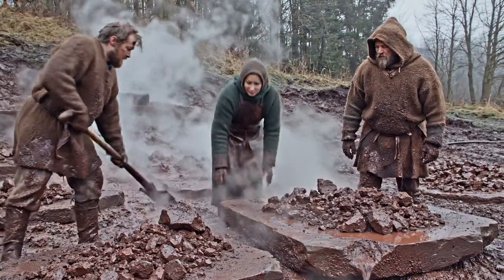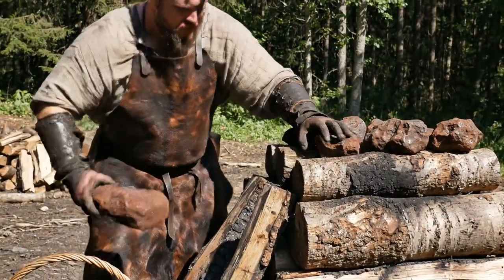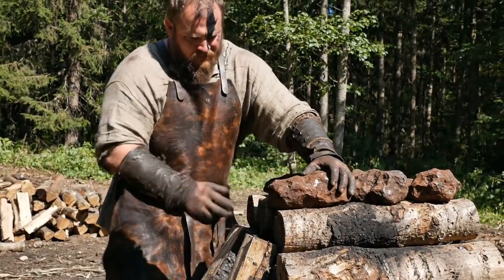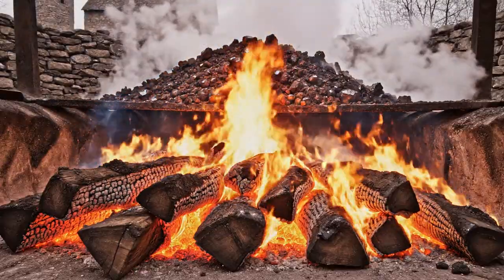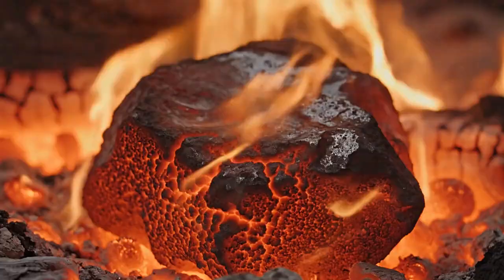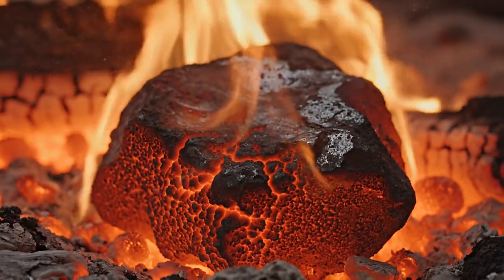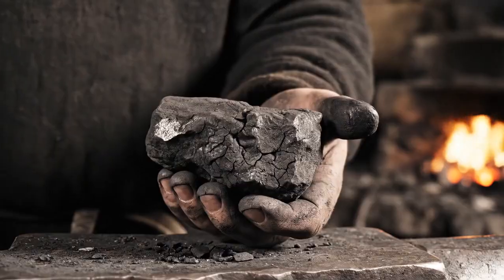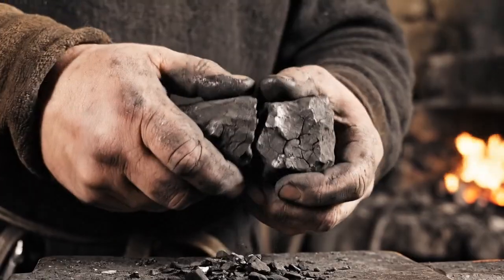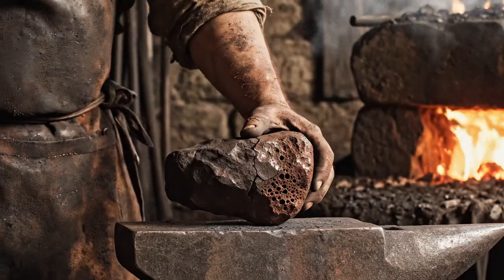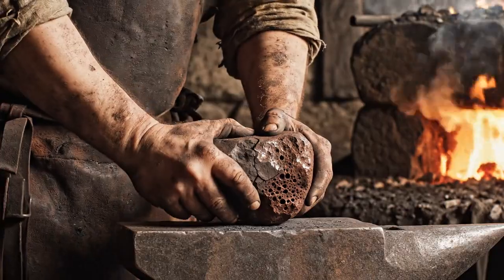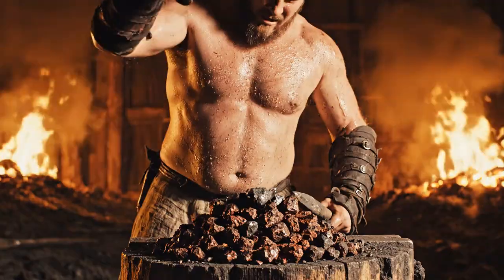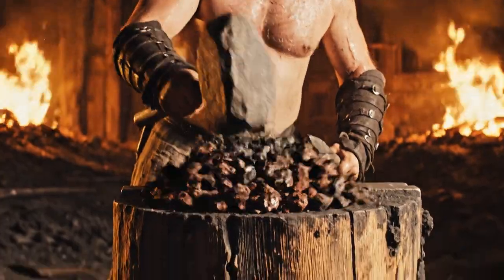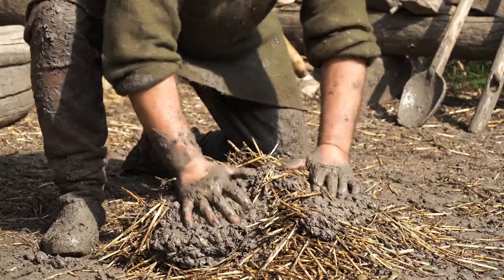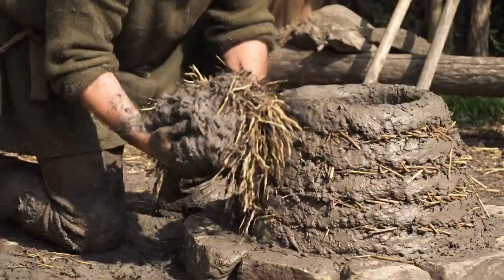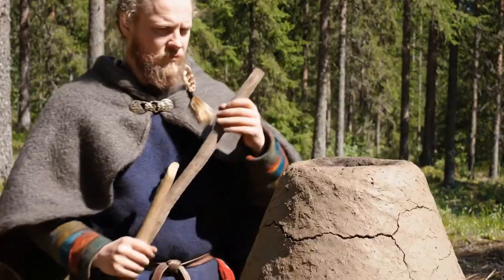The second stage was roasting. The collected ore was wet, often saturated with swamp water. Before it could enter a furnace, it needed to be dried and partially purified. The workers arranged the raw ore on a bed of firewood and lit it. The heat, reaching approximately 600 to 800 degrees Celsius, drove out moisture and burned off volatile impurities, particularly sulfur. Excess sulfur makes iron impossible to work with, causing it to become brittle and crack during forging. Roasting also made the ore more porous and easier to crush into smaller fragments, which improved the flow of gases during smelting. The third stage was the smelting itself.